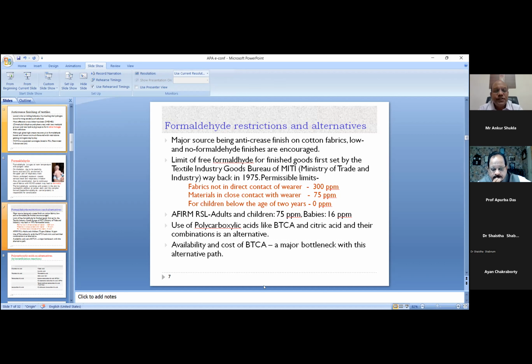In fact, the Ministry of Trade and Industry of Japan first came up with these restrictions. Fabrics which are outerwear, not coming in contact with the wearer's body, can have up to 300 parts per million formaldehyde, whereas the ones in contact with the wearer's skin, it is 75 ppm, and of course for children, it's 0 ppm as the skin is very sensitive. And the AFIRM RSL restricts the values to 75 ppm for adults and children, and for babies it is 16 ppm. So the only idea is to have an alternative to this formaldehyde.